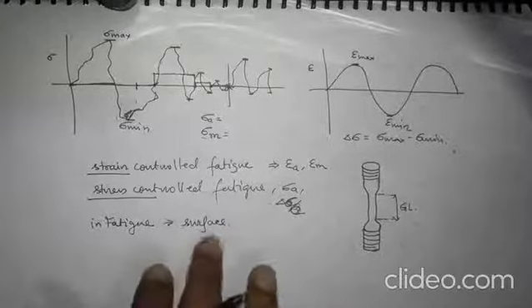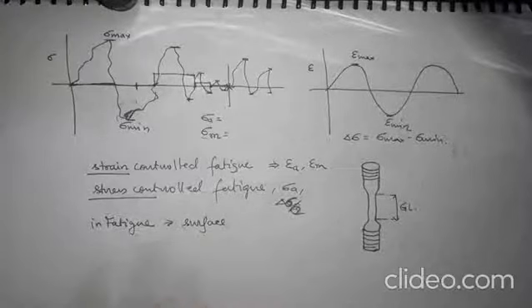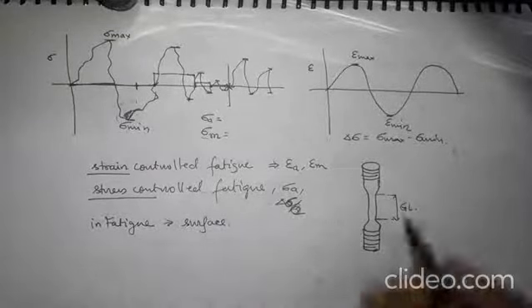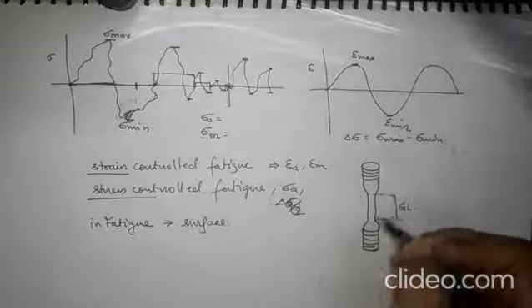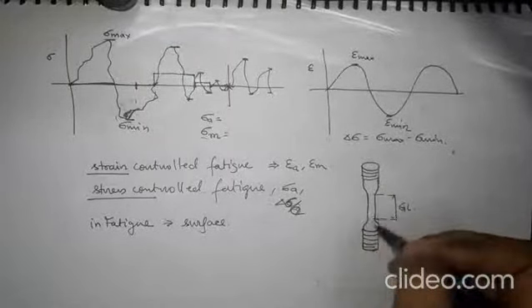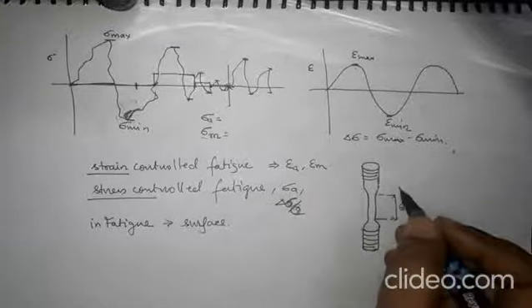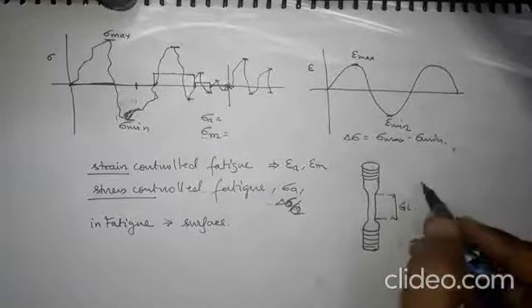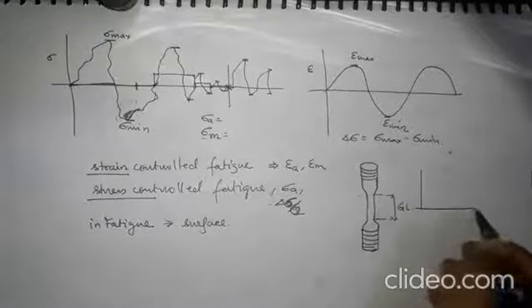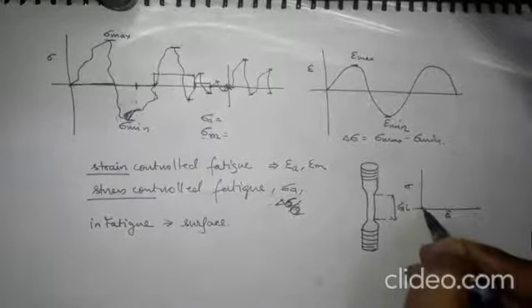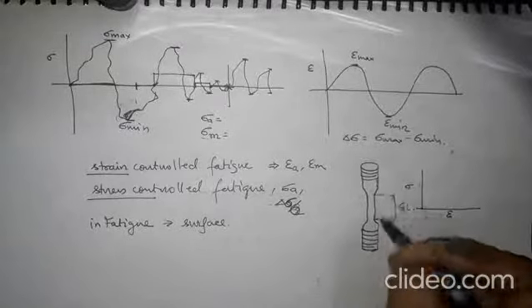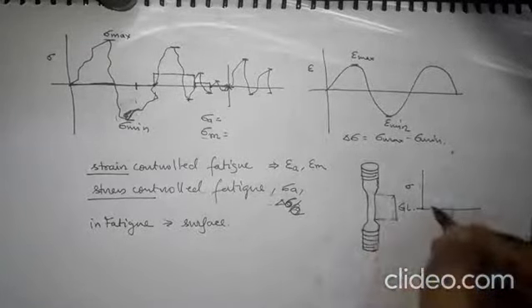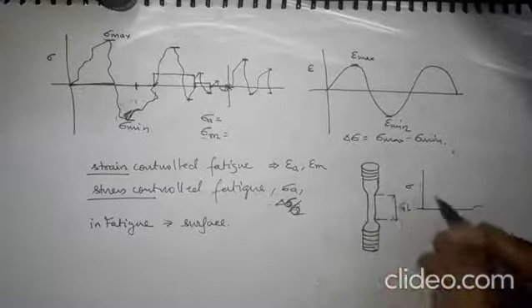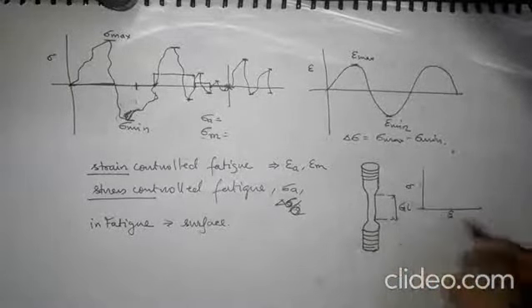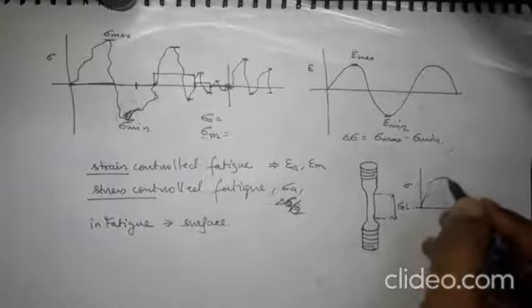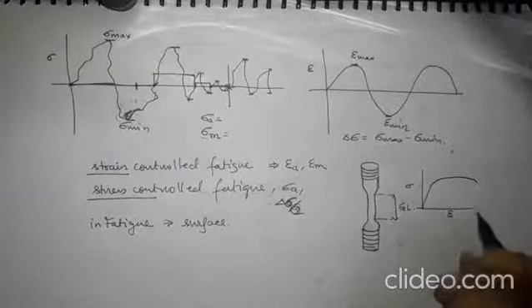But before going there, we have to understand something which comes from the fatigue testing. So what you do is you mirror polish the surface of the specimen, then you put it in the machine like we did in the tensile testing. The only difference is that in the tensile test we had a stress strain curve. So you apply displacement, and as a result you get the force from the machine. From that force you convert to stress and convert the displacement to strain, and you get this kind of behavior in tensile testing.